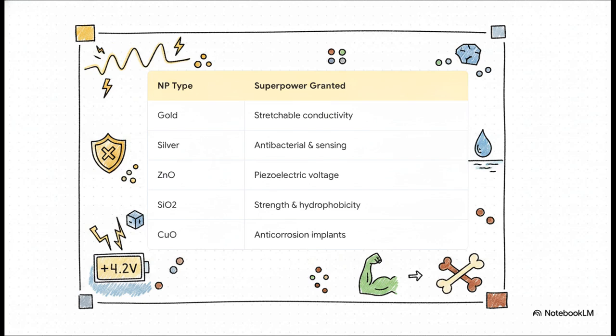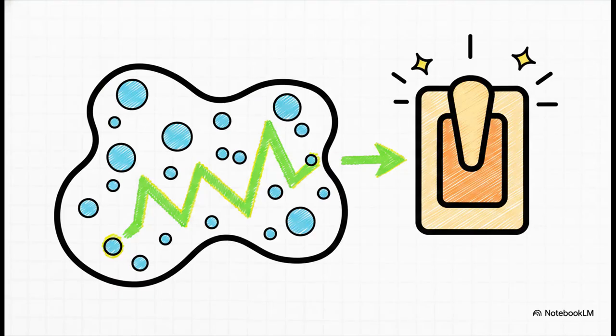Add gold nanoparticles and suddenly your rubber has stretchable conductivity. Add silver and it becomes antibacterial and can actually sense pressure. Mix in zinc oxide, and the rubber generates up to 4.2 volts of piezoelectric energy just by being compressed. No way, right? Silicon dioxide boosts mechanical strength, and copper oxide creates anti-corrosive temporary bone implants. It is just beautifully modular. But you can't just dump this magic dust in randomly. You have to achieve what scientists call the electrical percolation threshold.